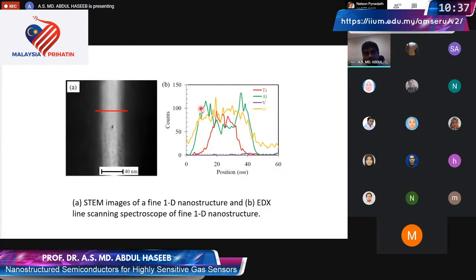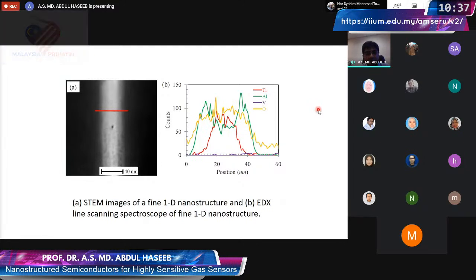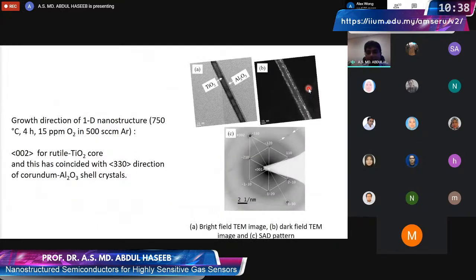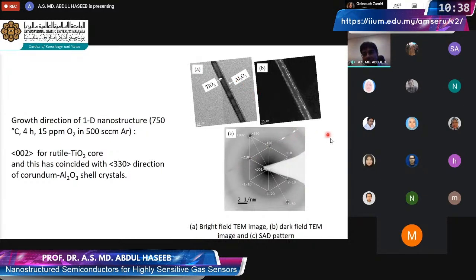So that tells us that the nanowire possibly has a core that contains titanium, which, on the other hand, is high at the middle. So it's probably titanium oxide at the middle and aluminum oxide at the outer surface. Indeed, when we do the electron diffraction, this is confirmed. In the electron diffraction pattern, all those spots belong to the titanium oxide, and the streaks that we see here belong to aluminum oxide. They appear as streaks because of the very small dimension in a direction perpendicular to the electron beam.